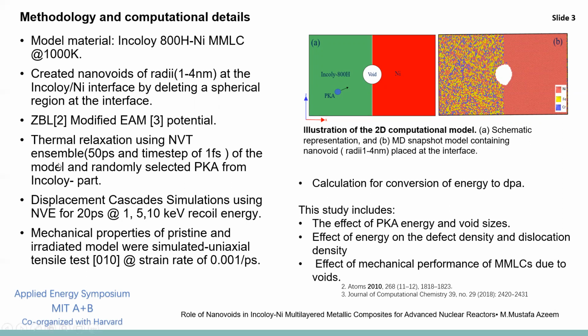We used LAMMPS to perform the simulations, and OVITO is used for visualization purposes. Initially, we relaxed the structure by using NVT ensemble at 1000 K, which is the operating temperature for fast reactors. Three sets of incident energies, 1, 5 and 10 keV, were used